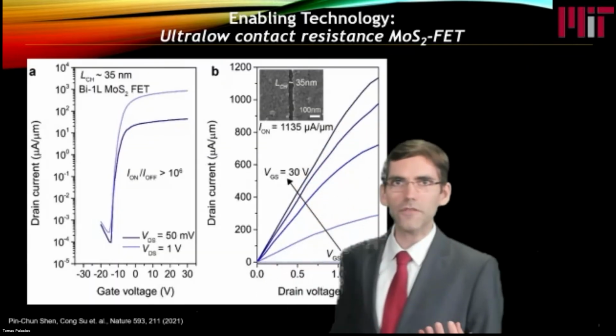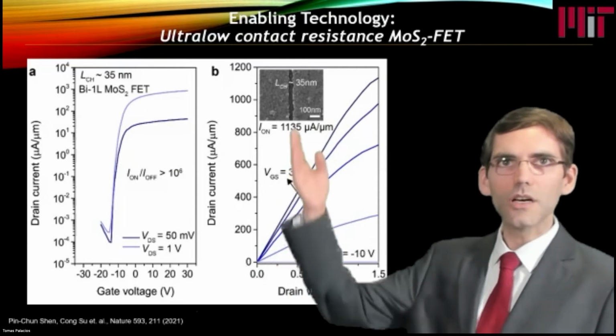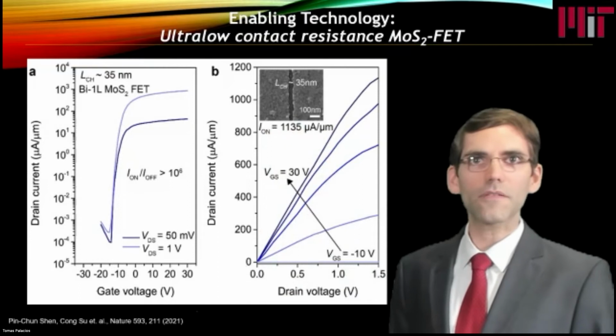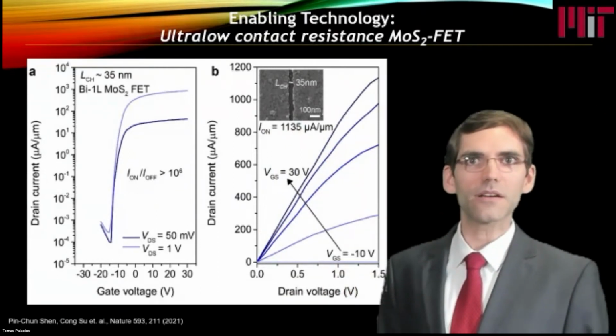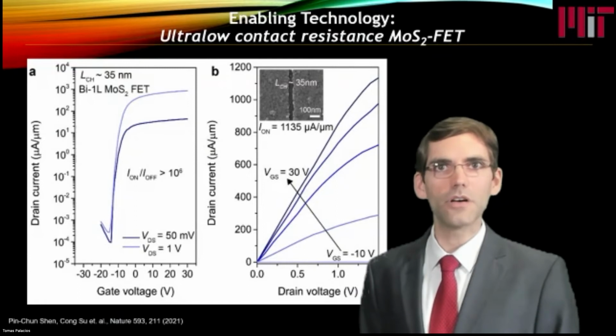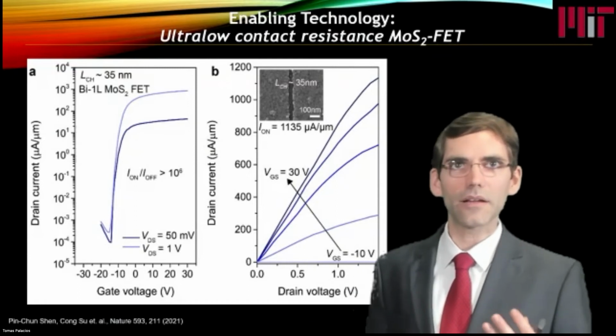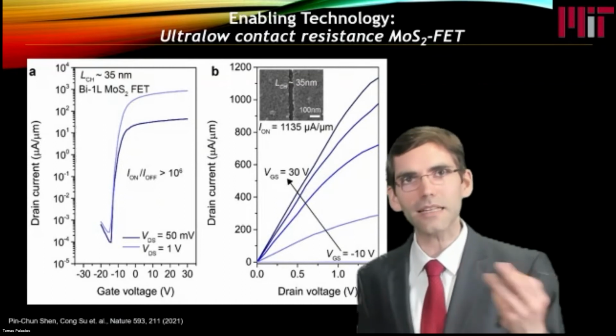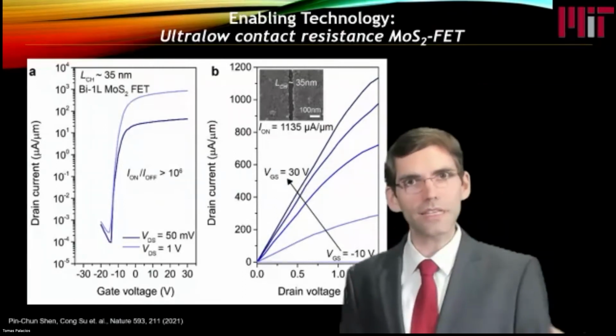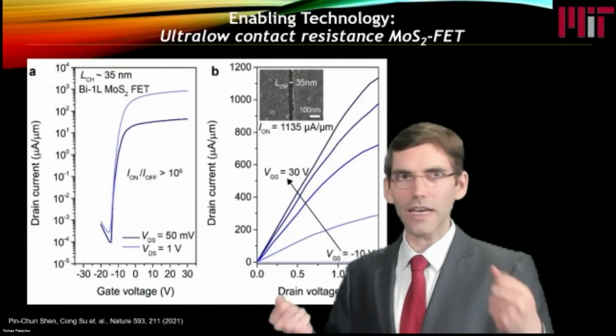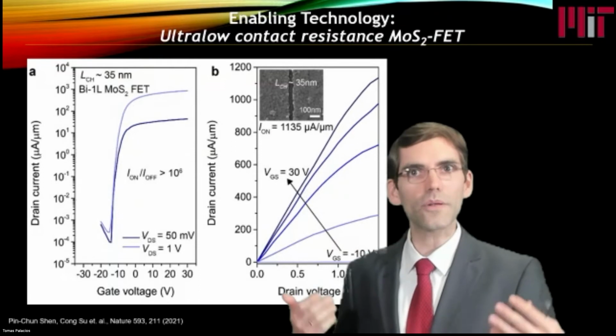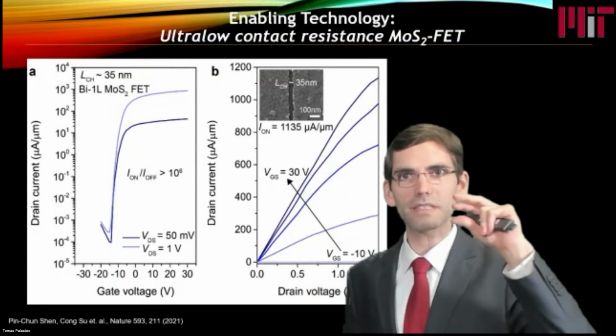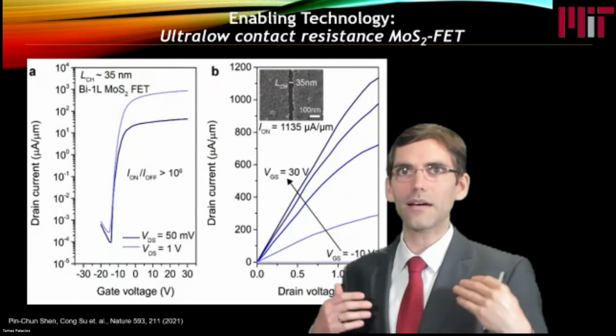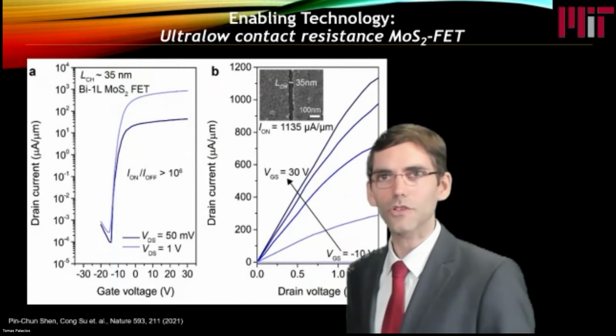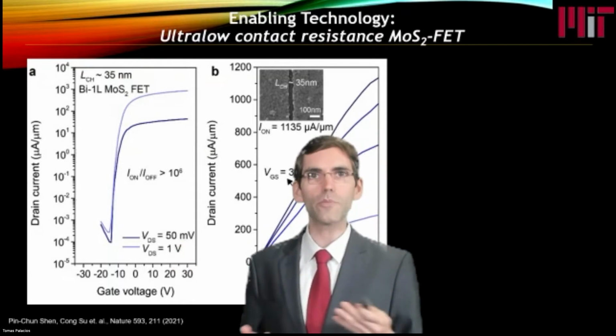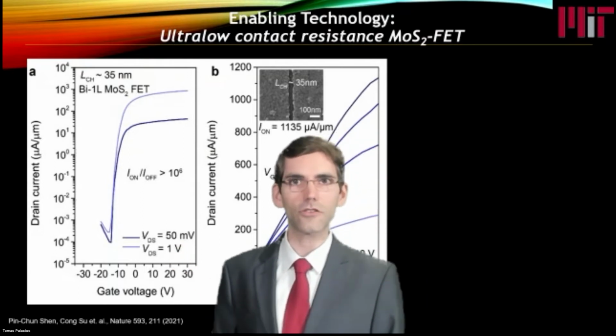And with that, we were able to fabricate molybdenum disulfide transistors with on currents in excess of 1 amp per millimeter, or 1100 microamps per micron, which is the highest current density reported in 2D materials. And we think we are just starting to scratch the surface of what we can do with this material that can be deposited on any substrate at temperatures below 300 degrees C, and that because of its extreme thinness, you can have outstanding electrostatic control. So I believe this kind of material system is going to play a very important role in the future of semiconductors.